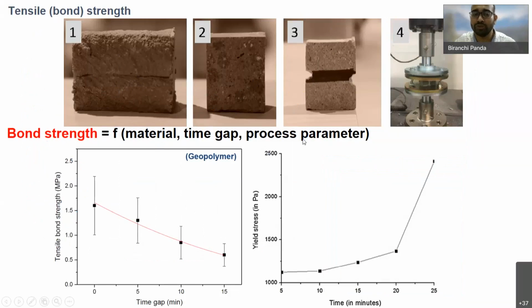Let me explain this to you. Suppose the material is hardening very fast; in that case, even a gap of 5 minutes between these 2 layers is going to create a very poor bond strength. But if the material is very sleepy, not hardening immediately, even if you delay 5 to 10 minutes, you will still get acceptable bond strength. So how fast your material is hardening and what the time gap is, these two are highly dependent and affect your bond strength.